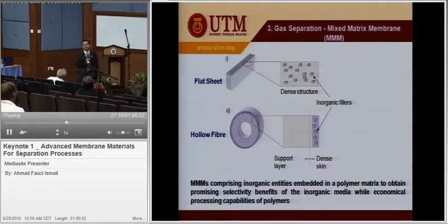Now we come to the mixed matrix. How do we develop mixed matrix membrane material, which is now a booming research area in this technology? So how do we do that? The mixed matrix comprises inorganic entities embedded in a polymer matrix to obtain promising selectivity, in other words, adopting the easy processing characteristics of polymeric material with the high selectivity molecular sieving effect of inorganic fillers, like zeolite, carbon nanotubes, carbon molecular sieve. So we mix that.